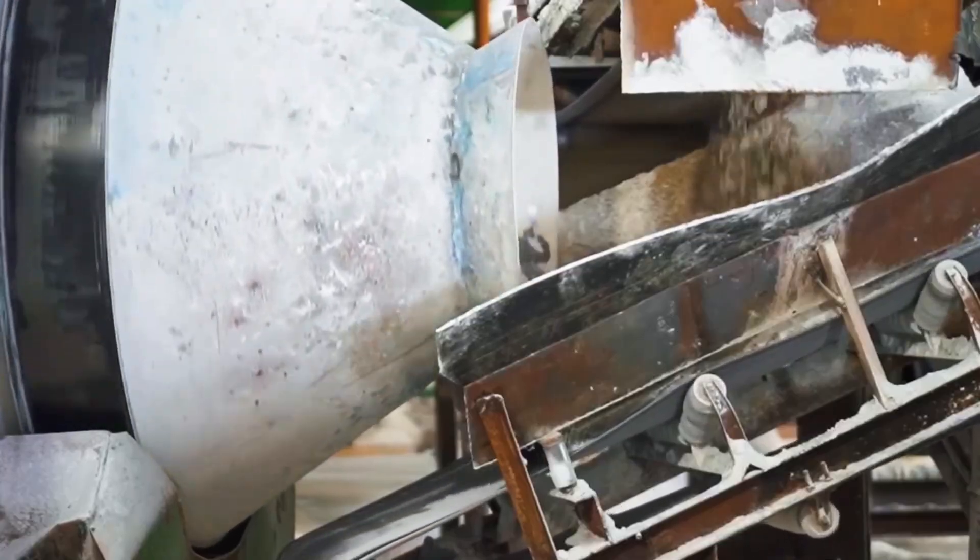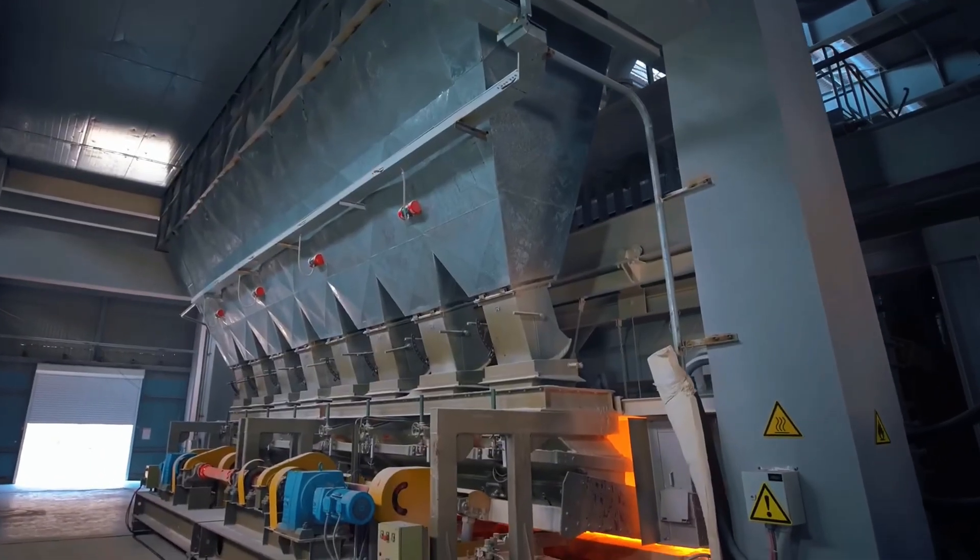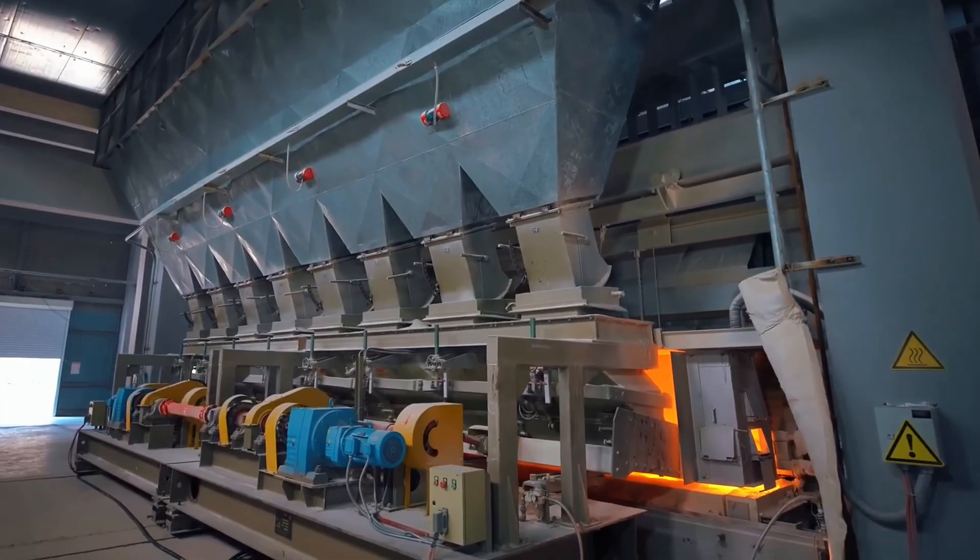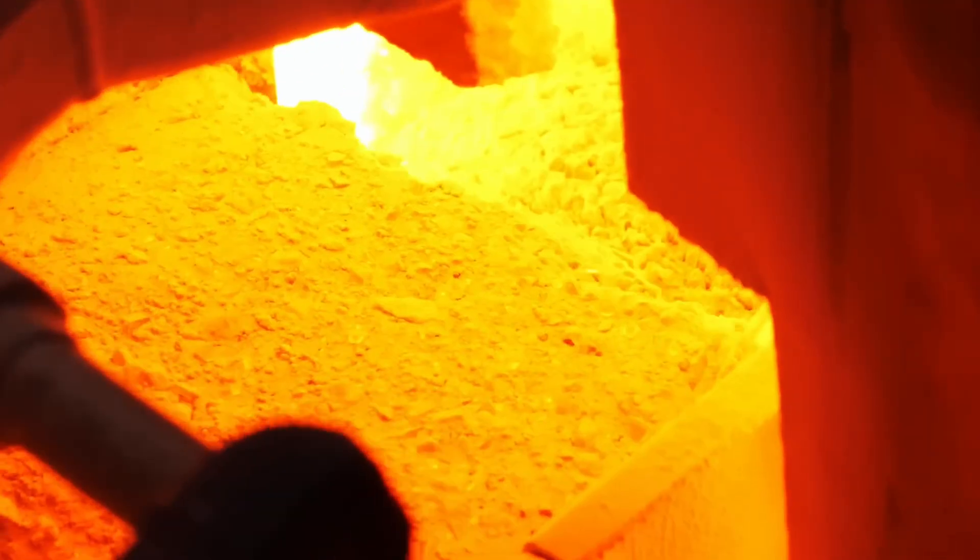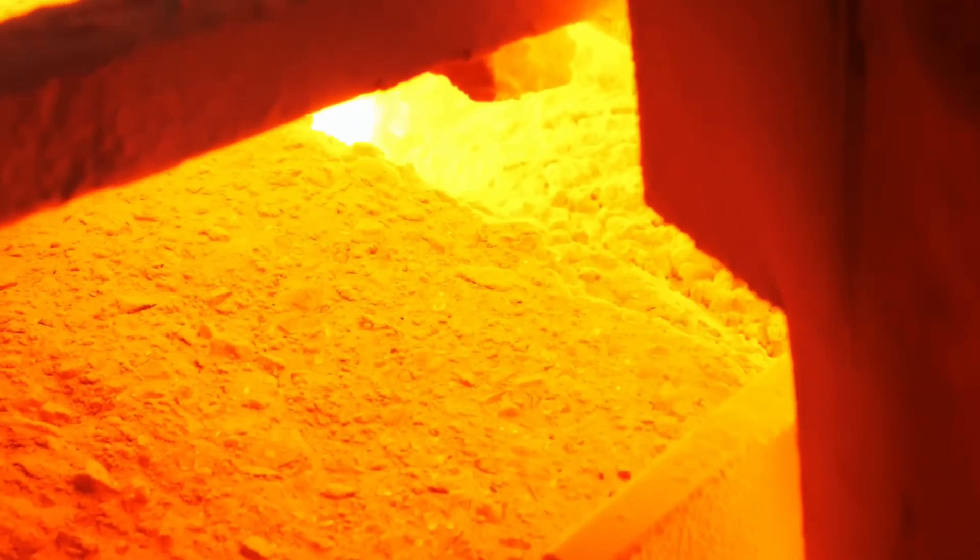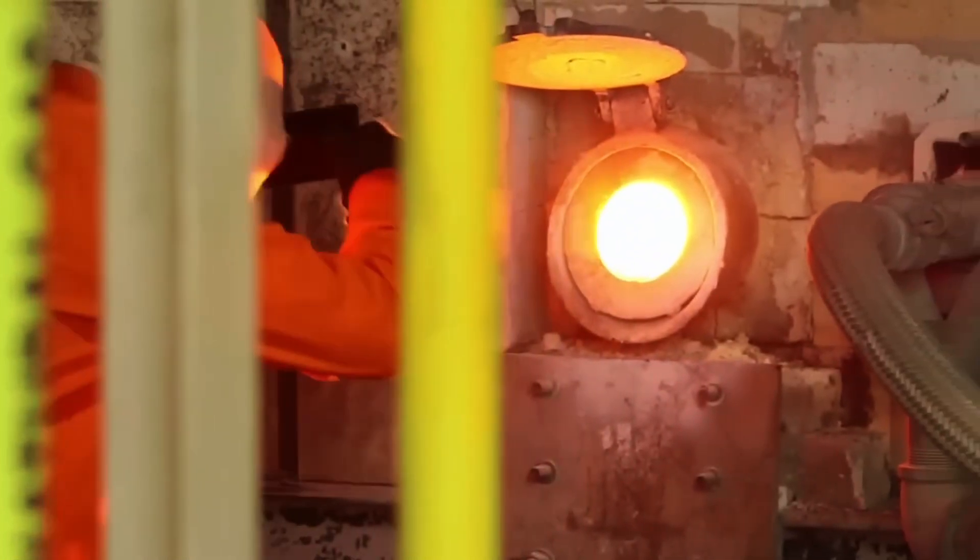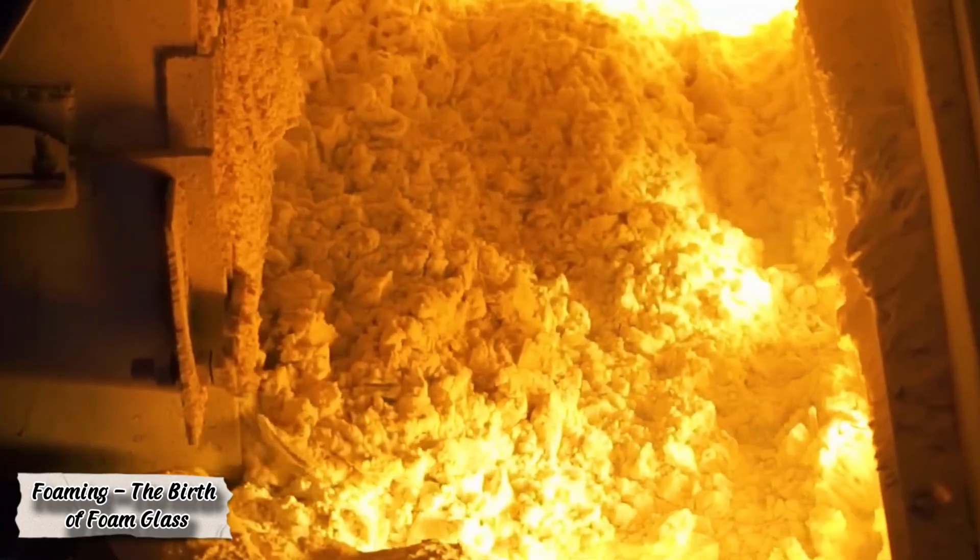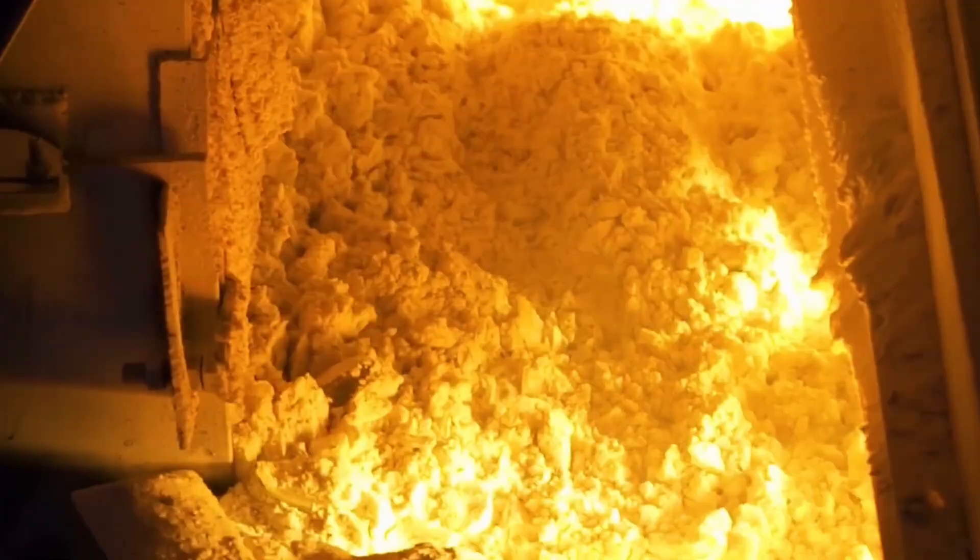Engineers monitor every parameter: temperature, feed rate, and gas concentration. Mistakes are unacceptable here. If the temperature is too low, the glass won't foam; if too high, the bubbles will burst, leaving the material brittle and weak. This is the heart of the entire process.